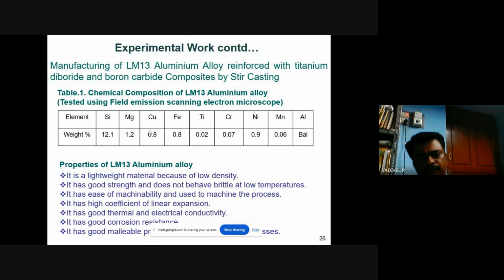Before manufacturing these hybrid composites, before starting the work, we tested using FESEM analysis, field emission scanning electron microscope, the elements which are present in the LM13 aluminum alloy. The weight percentages are given here. The elements present in the LM13 aluminum alloy are silicon, magnesium, copper, iron, titanium, chromium, nickel, and the balance is aluminum.